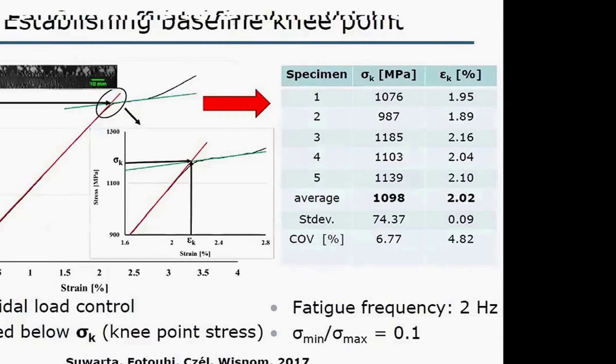So we get this stress-strain response here, where we get the plateau region. We tested a number of specimens here and got the average of that. So that knee point stress was determined to be around 1100 megapascals. So then we do the fatigue under load control at below that point there. We're taking pristine material initially, and we fatigue it at, let's say, 80 or 90% of that knee point strain to see how it behaves.